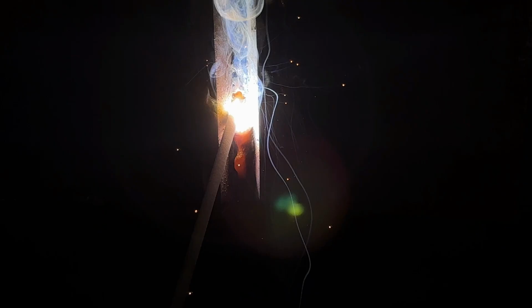At this stage we've got a bit more weld metal in there, so we've got a bit more room to work with. So we increase our amps to 110 and our key focus is fusing properly into the side walls as we progress upwards. We need to maintain a flat and even welding profile throughout. This is where the skill comes into play. Your weave should be consistent, ensuring you keep your weld ripples tight between each weave. This ensures good penetration into your previous run and sidewall fusion into the plates, which gives a neat appearance without excessive build-up.